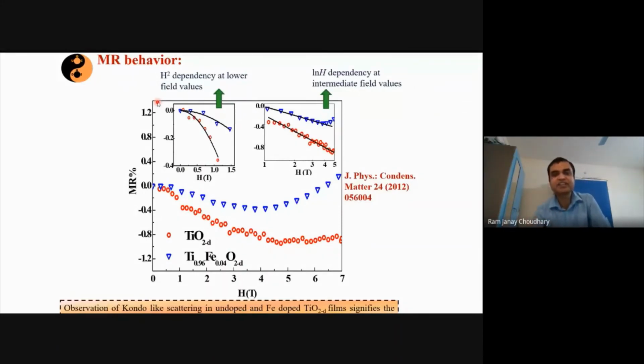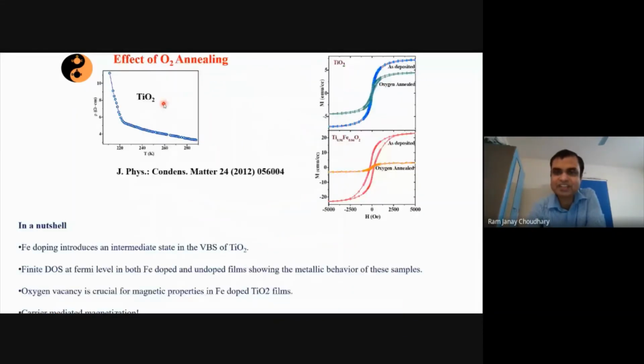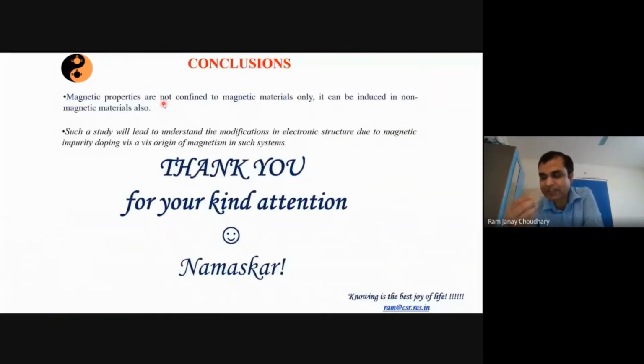That change in resistance is measured by magnetoresistance percentage. So from these observations, you can see that the material actually shows magnetization after doping iron in this system. The dopant iron which we had in the system was substitutional in nature. It was carrier mediated magnetization. We had magnetization, but not because of the iron metal cluster.